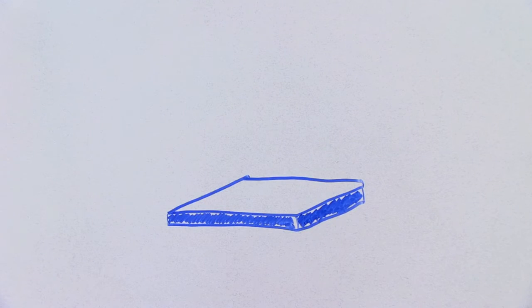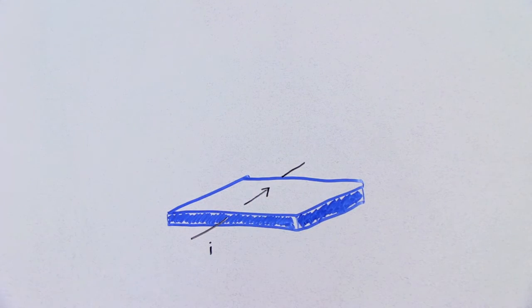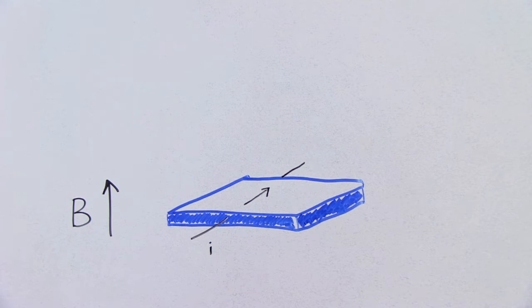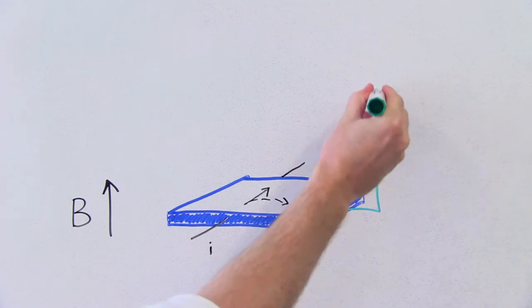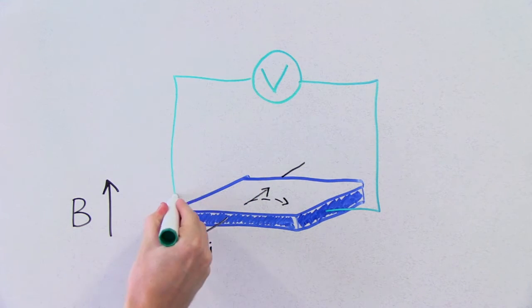The way you measure this in a conventional semiconductor is to do a Hall effect experiment. In this experiment, we flow current through our sample and apply a magnetic field. The magnetic field deflects the electrons, and we measure this as a voltage across the sample. This voltage can be related to the drift mobility in classical semiconductors.